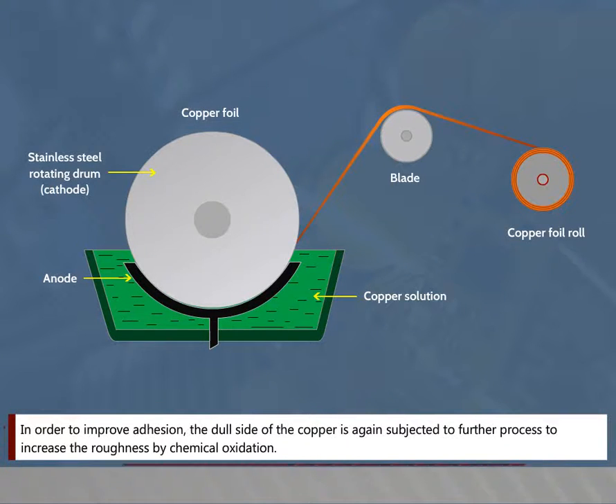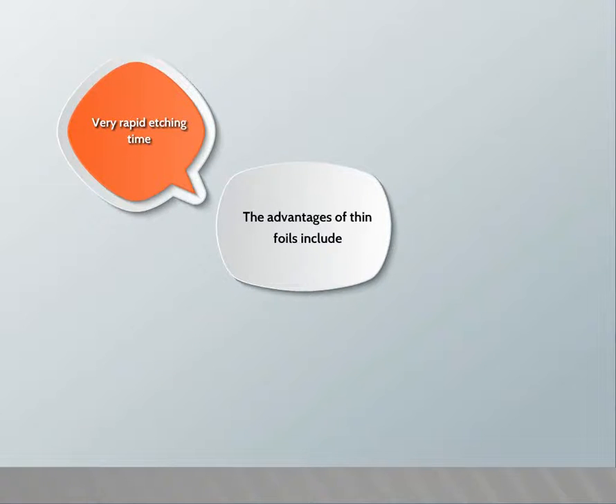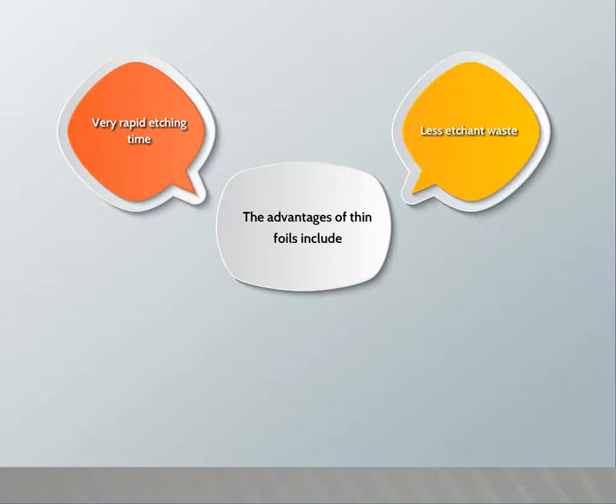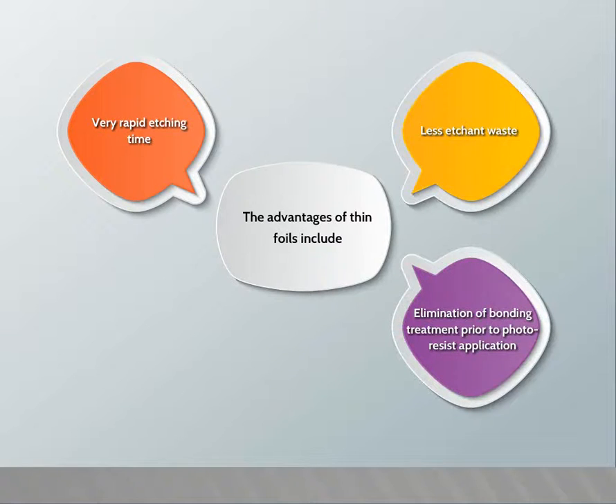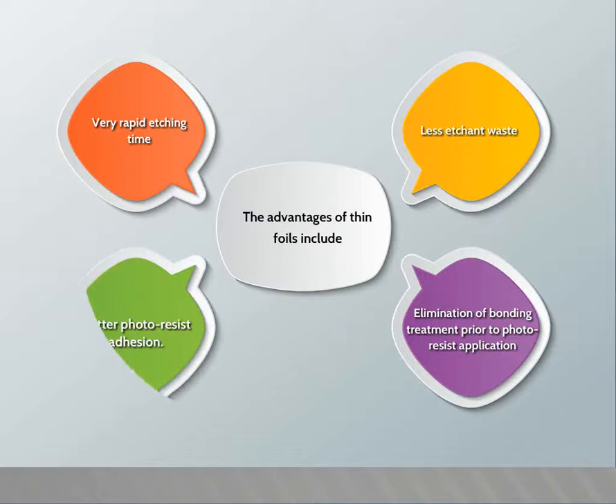In order to improve adhesion, the dull side of the copper is again subjected to further process to increase the roughness by chemical oxidation. The advantages of thin foils include very rapid etching time, less etchant waste, elimination of bonding treatment prior to photoresist application, and better photoresist adhesion.